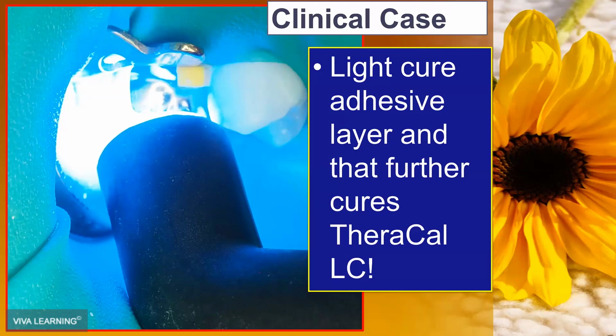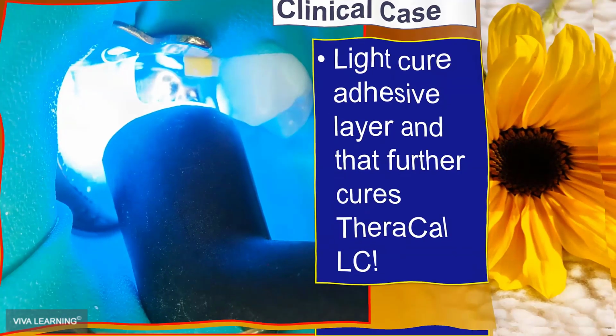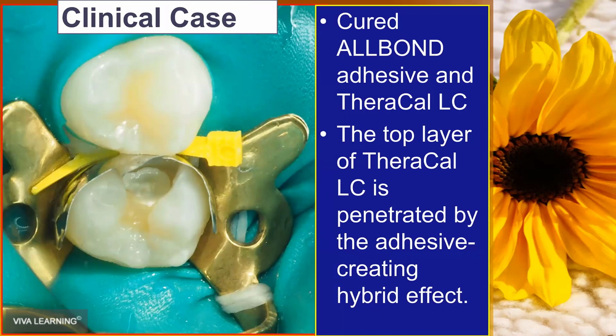And the ideal situation is to have the TheraCal LC on the dentin, the deep caries, then the adhesive, the Scotchbond Universal, which penetrates into the TheraCal LC. So when you light cure it, you have this extremely strong, highly resin concentrated outside layer of TheraCal LC, where the inside layer is still very hydrophilic and has a high concentration of tricalcium and dicalcium silicate. Then you see it right there. So that top layer of the TheraCal LC is penetrated by the adhesive, creating the hybrid effect. Look at the hybrid effect.